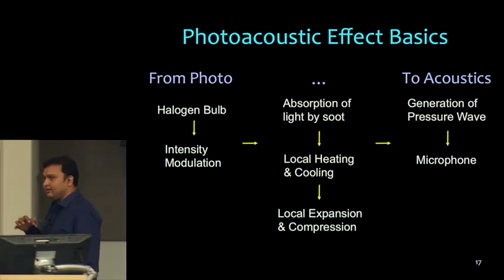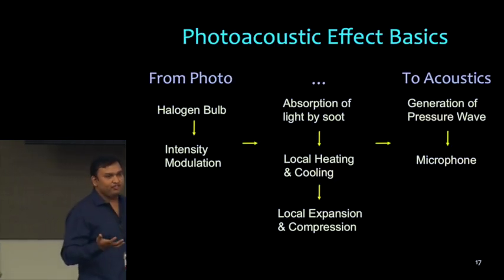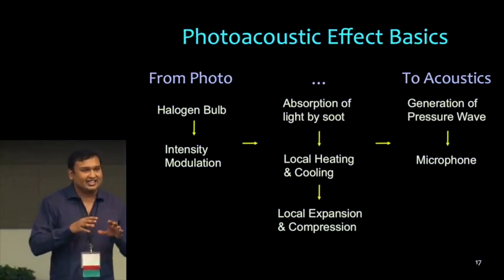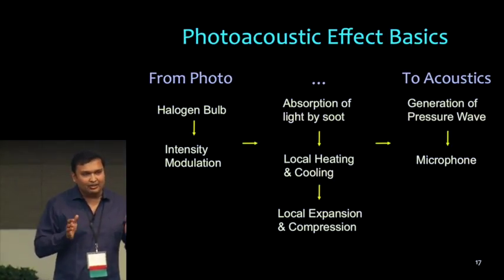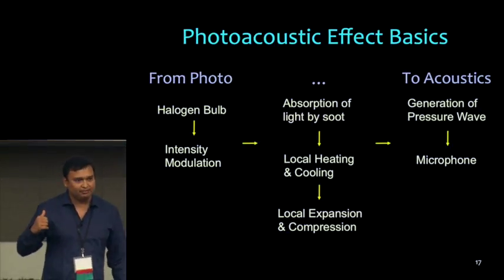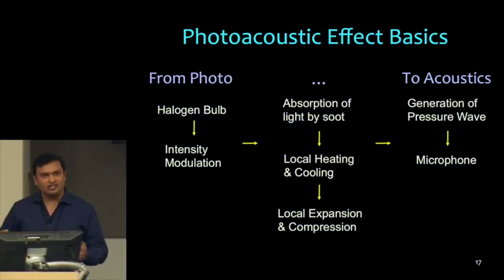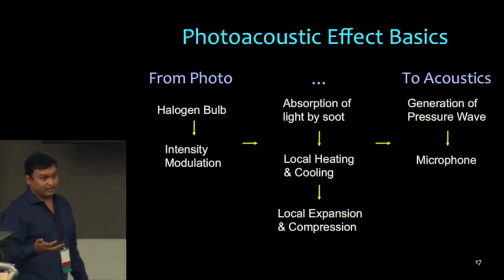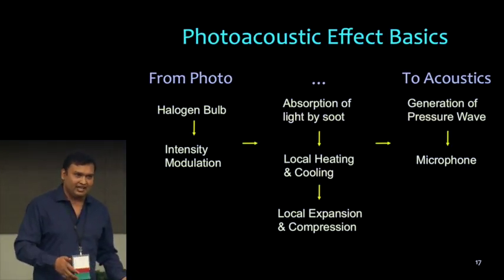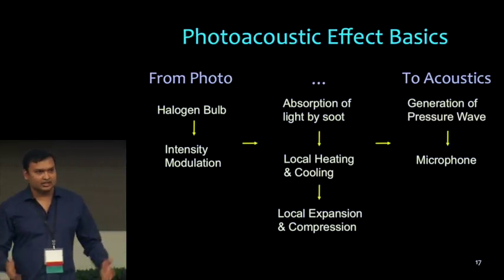In fact, you don't need a lot of preparation. In a diffuse reflectance-based approach, if you have a material that scatters a lot, you need to first prepare and condition it before you can test it. For a photoacoustic-based approach, you don't need it, and there is existing literature that talks about it. So there are a lot of reasons why you'd prefer a photoacoustic-based approach, which means converting the light to a sound wave and then analyzing the sound wave rather than directly using a photoelectric effect. That is essentially the basic reason.